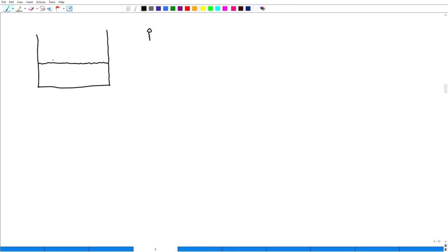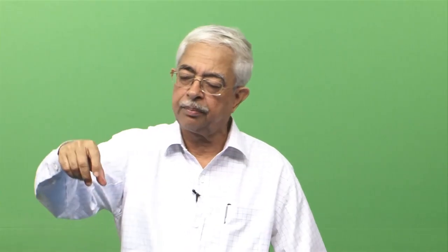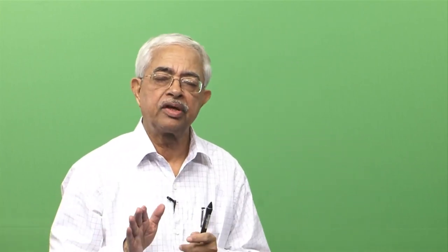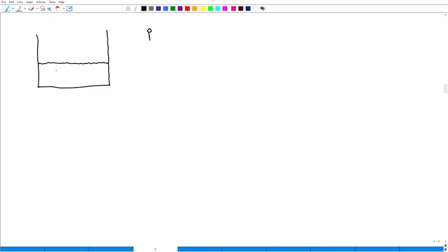So, I dissolve it in dichloromethane, make the solution, take it in a pipette and put it drop wise throughout and then leave it as it is. After leaving at room temperature, what will happen? Dichloromethane will vaporize. So now I have no dichloromethane here. What I have is pure water and air. I have water and air. So, I am now studying what happens to an amphiphile at the air-water interface.